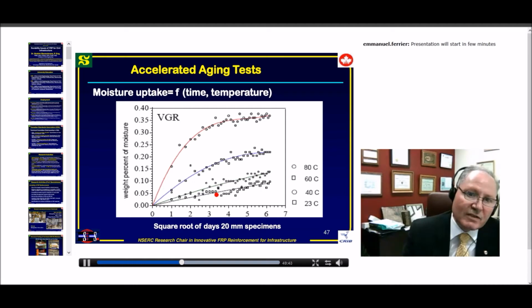This is also kind of the result that we can achieve. This is about moisture penetration, and as you can see, as a function of the temperature, the ambient, you can see it here, 23, 40, 60, and 80. So as you are increasing the temperature, of course the rate of diffusion is increasing, and also the maximum moisture is increasing, as you can see. This is why the temperature is being used as accelerating aging. So it will happen exactly the same thing in the specimen that you will be testing.